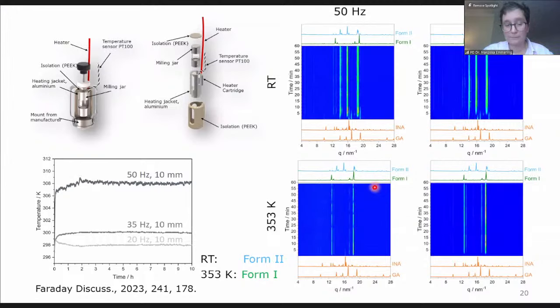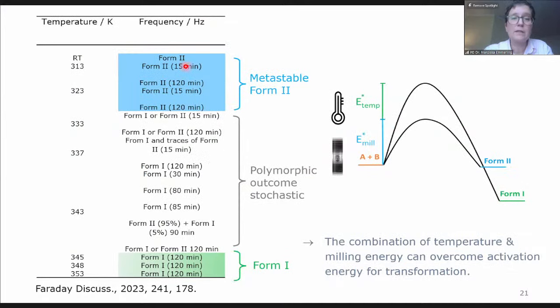So based on that data, we could find out with other measurements that there seems to be an upper and lower barrier where we can decisively produce one or the other polymorph just by tuning the temperature. So not only the milling energy, but also, let's say, kicking it over the hill by adding a bit more temperature. And there's an in-between area where the outcome of the polymorphism is more or less stochastic, which is also clear if we have very close energy barriers for both polymorphs.